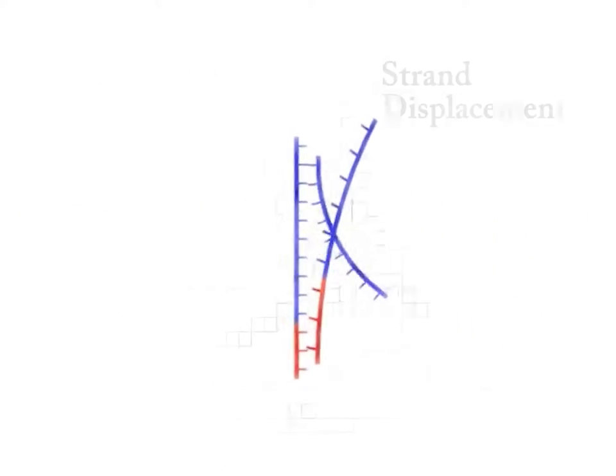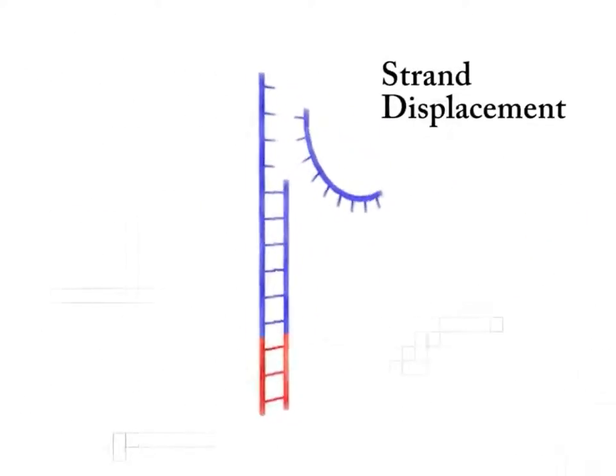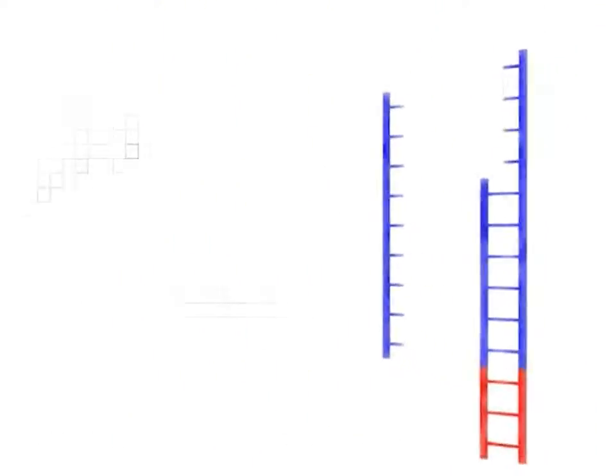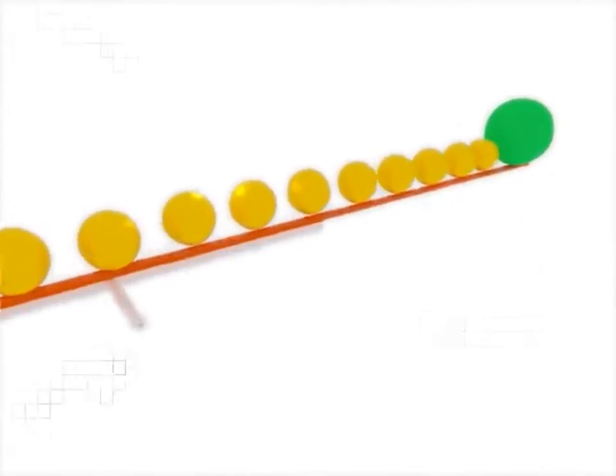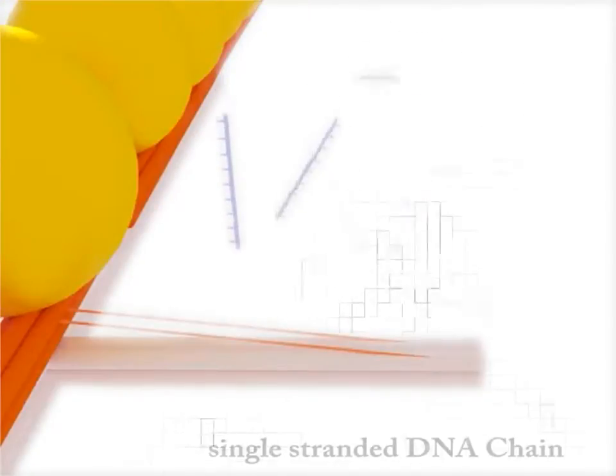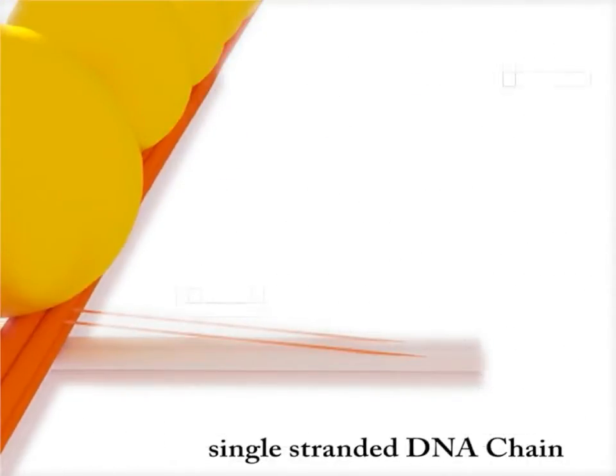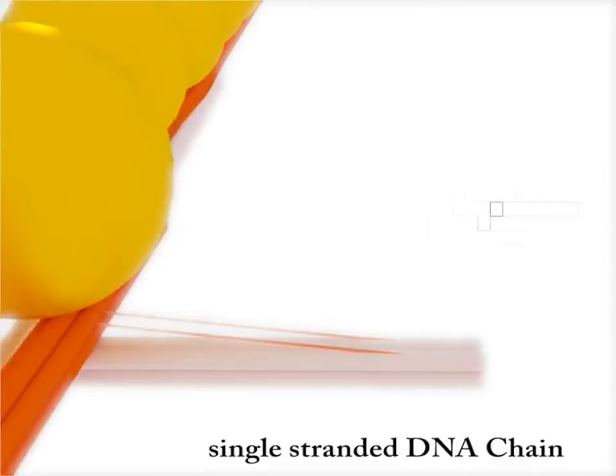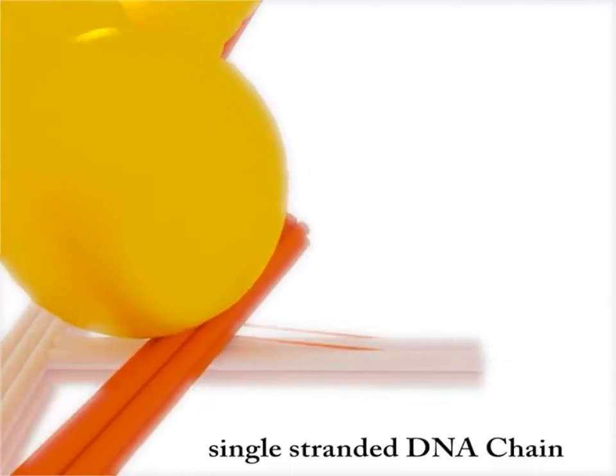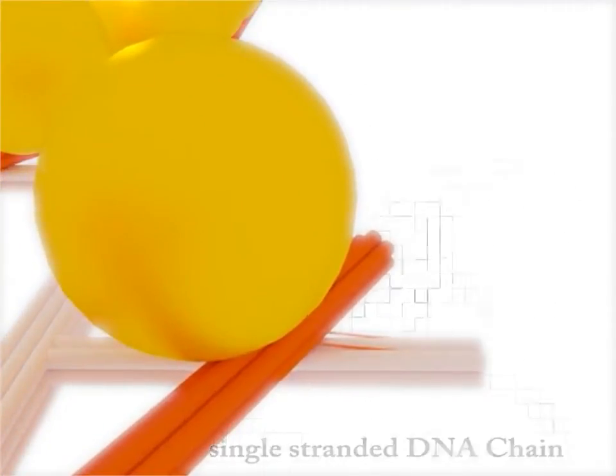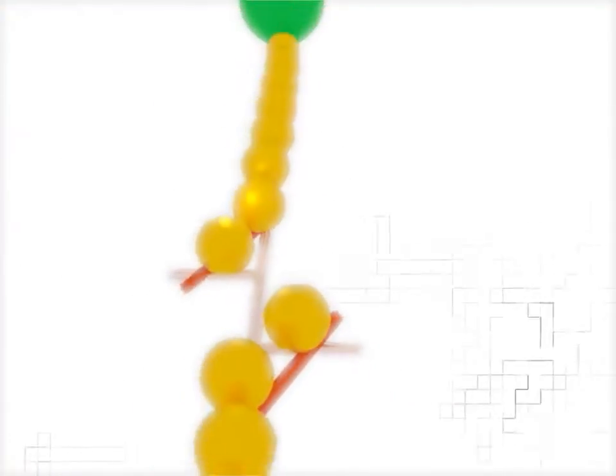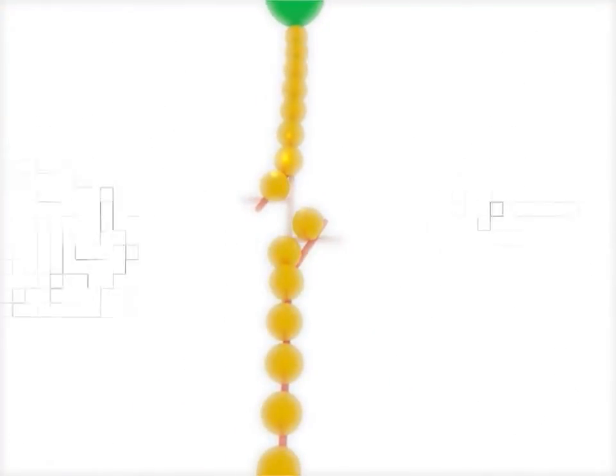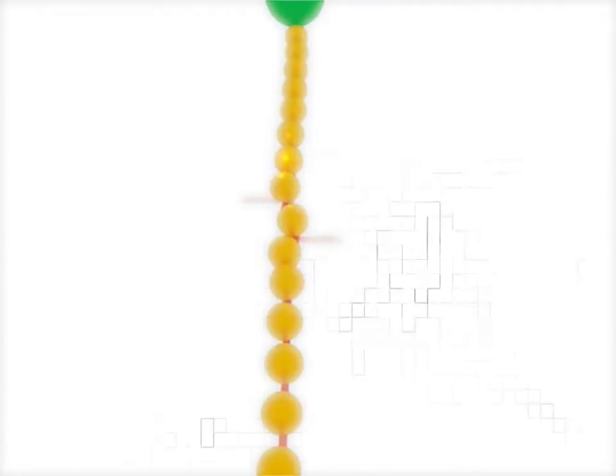Strand displacement and reversible hybridization provide a mechanism to create an on-and-off switch. Complementary single-stranded oligonucleotides hybridize with the single-stranded chains, pulling the waveguides apart. Plasmon coupling is now interrupted. By removing the complementary oligonucleotides, the waveguides are free to move back into the initial state and the plasmon coupling is restored.